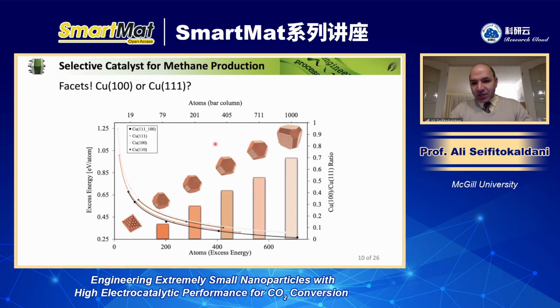So what we realized was that when the particles are large, you have a combination of different facets, 111, 100, and 110. But the 100 facet was dominant compared to the 111. So the ratio of 100 to 111 just kept increasing as the particle size increased. But on the opposite side, when the particle was extremely small, you don't see 100 or 110 or 211. The particle is most stable if we have only 111 facets. So this pyramid shape is the smallest particle that we can have, with just 19 atoms, for example, and shows the highest stability within this range.